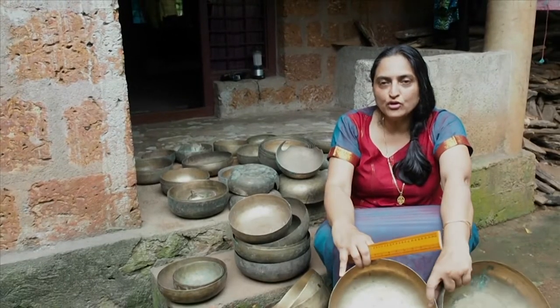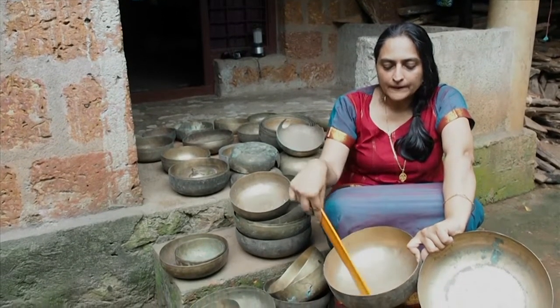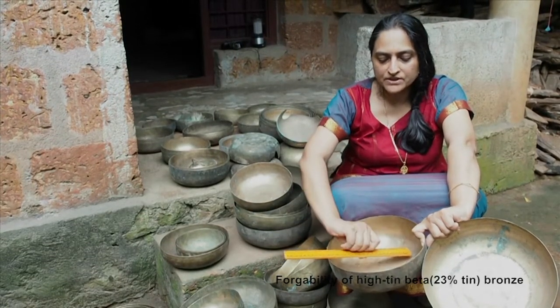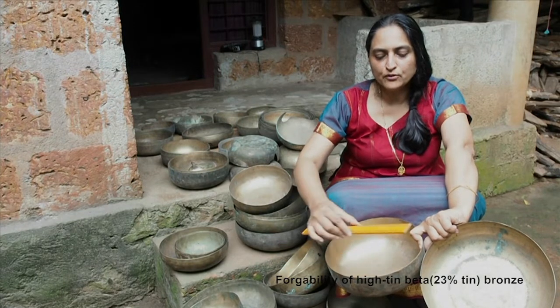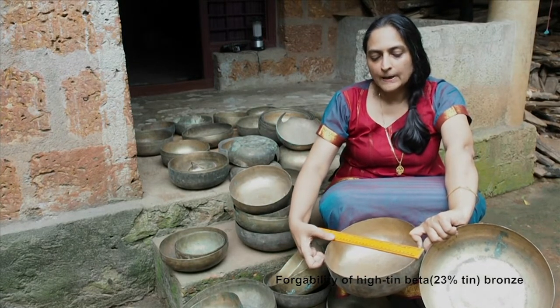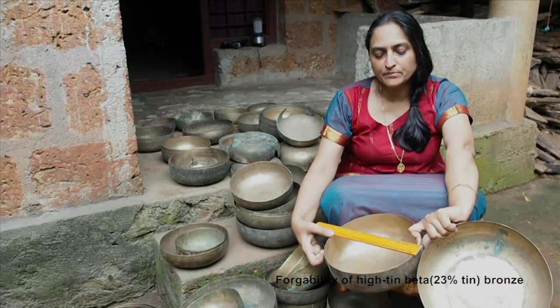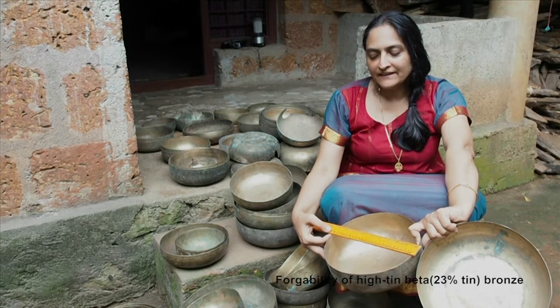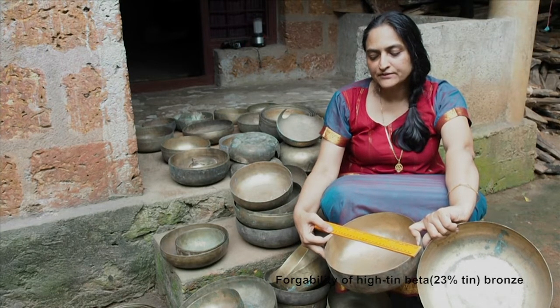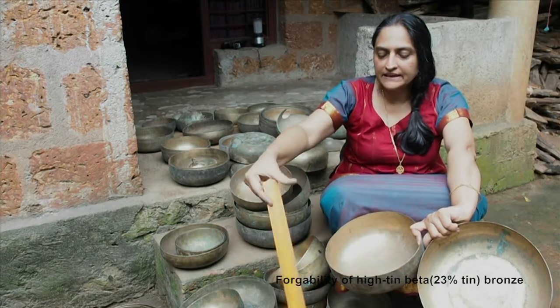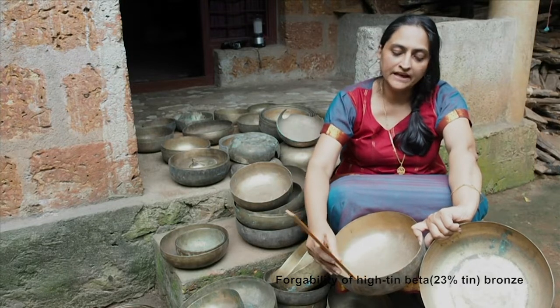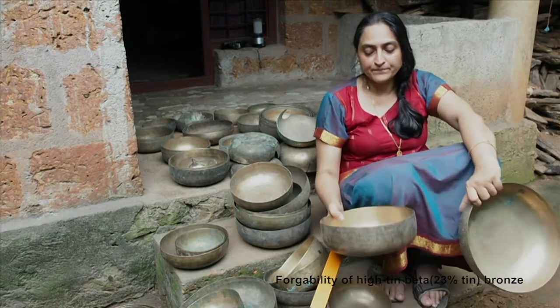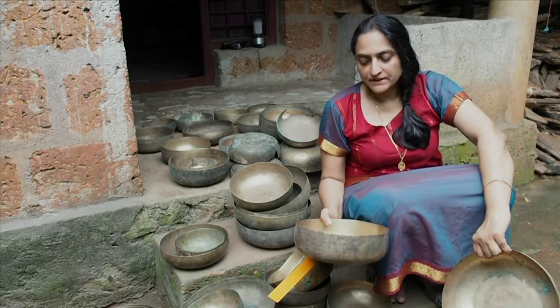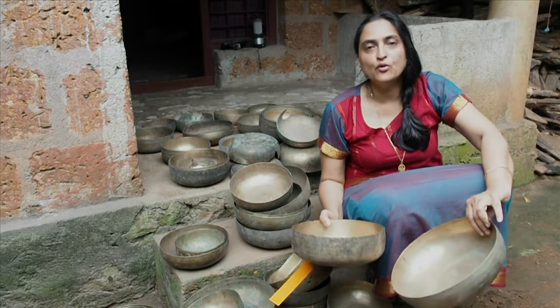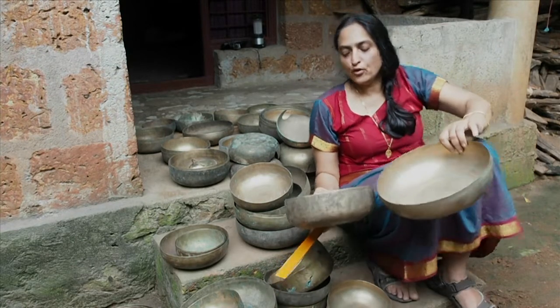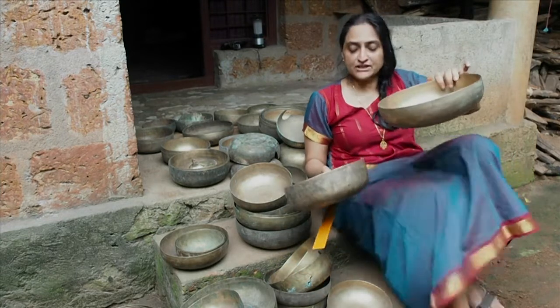And these had been made by forging an ingot of about, you can see here, for example, this very large vessel, which has been forged by starting with an ingot of about 13 or 14 centimeters. And then this 23% tin bronze is hot forged at a temperature range of about 600 to 700 degrees centigrade. And then they were able to forge a vessel of about 24 centimeters in diameter and about 8 to 9 centimeters in height. Normally bronze cannot be forged this much, but they had developed very great skills in forging high-tin bronze. Normally you never find such heavily hot-forged high-tin bronzes, and these are some of the most extraordinary examples.